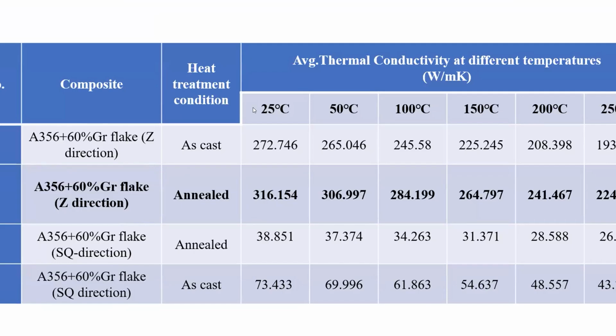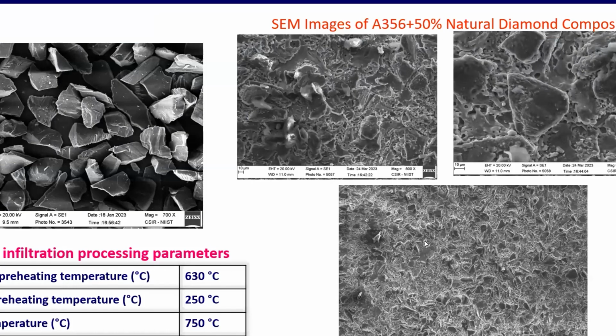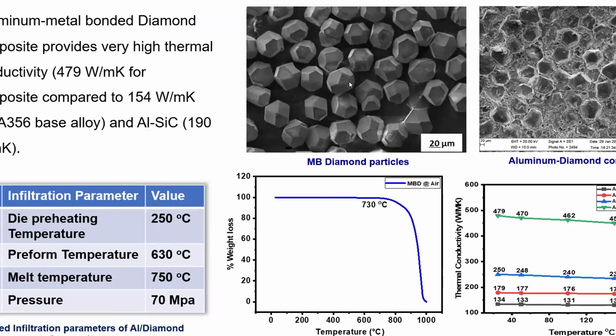Again, we tried other types of reinforcement. For example, diamond particles. We procured natural, synthetic, and metal bonded diamond particles and made the composite. You can see very clearly the distribution of the particles here. And this is the microstructure of the metal bonded, very crystalline diamond particles, which are again embedded in an aluminum matrix. We evaluated all the thermal properties of these materials. Even this diamond is stable up to around 800 to 900 degrees C in an air atmosphere.